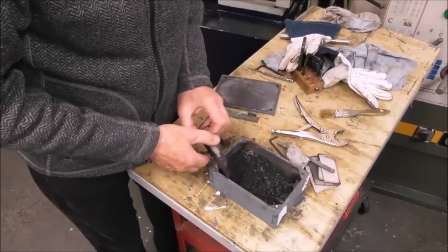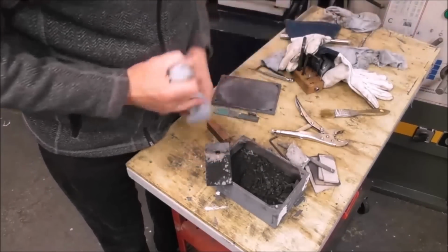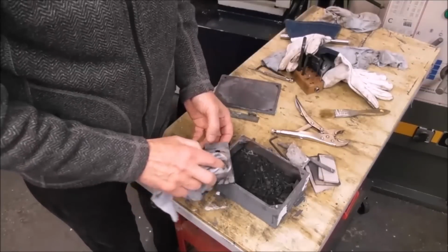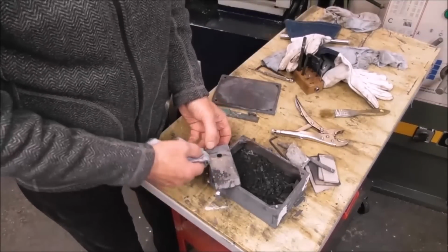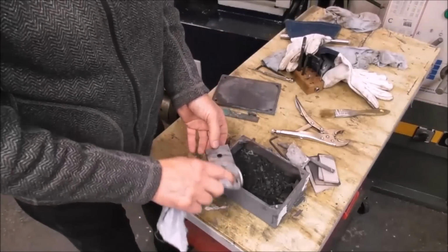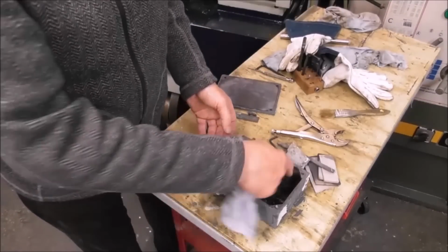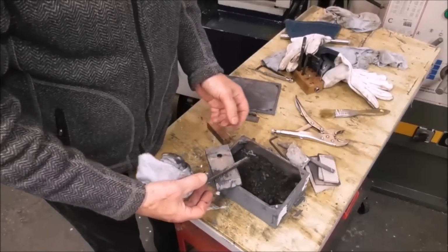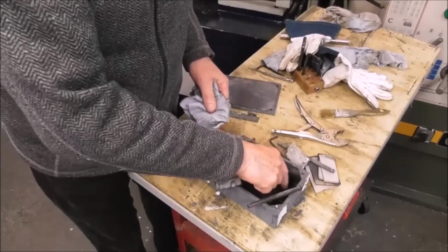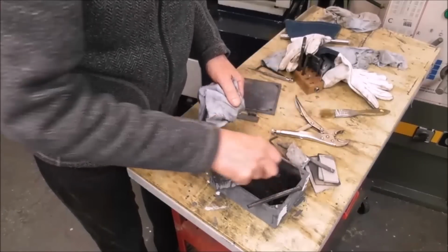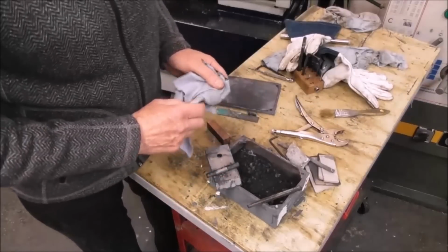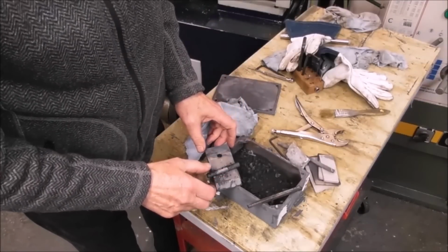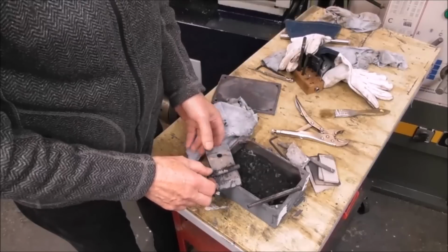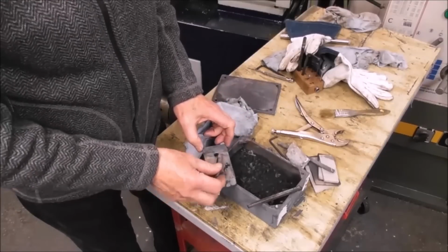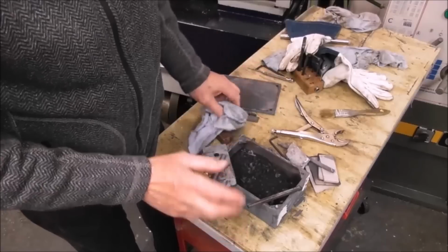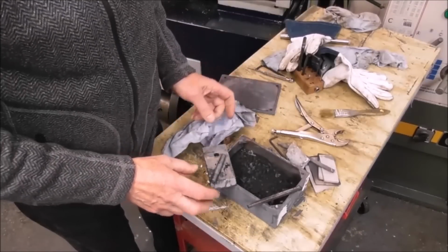These are quite hot, but I'll have a good look at these, and of course I won't know until I've tried hardening them, heating them up to the hardening temperature and quenching them, and then I can do some tests, for example with this part, to see how deep the case is. I've got different parts in here, ouch, and I can check them out and see just how good the surface hardening is. I'll get back to you on that, but quite pleased with the looks of it. It's not badly oxidized, so the lid or the charcoal has presumably sealed out enough oxygen for that side of it to work well.